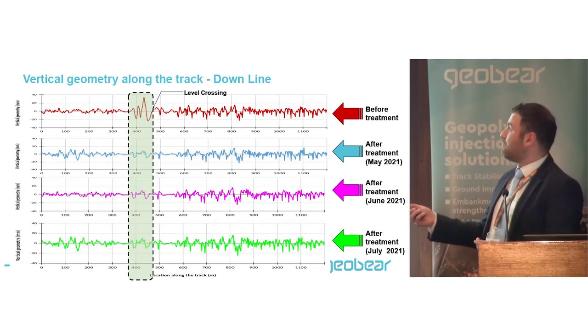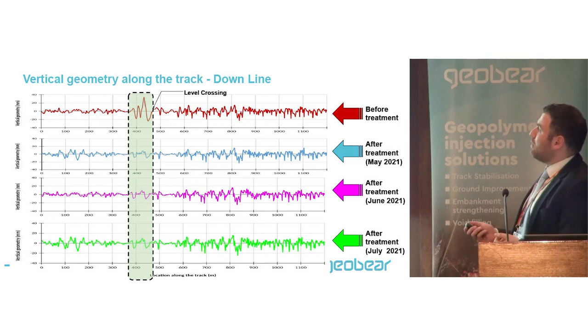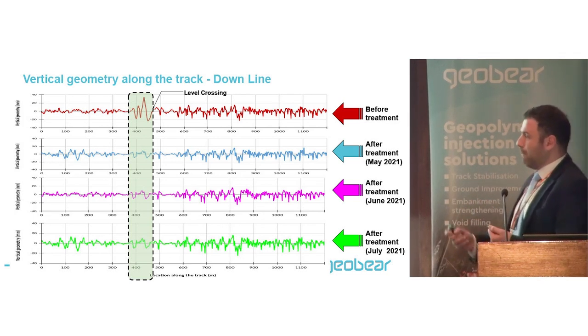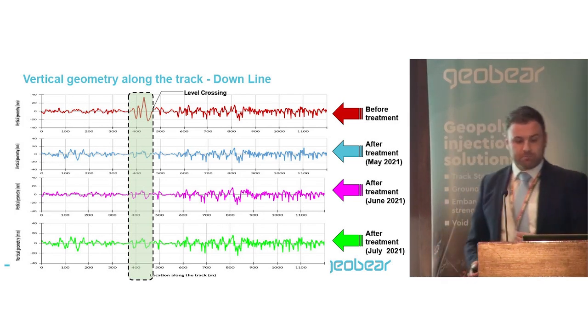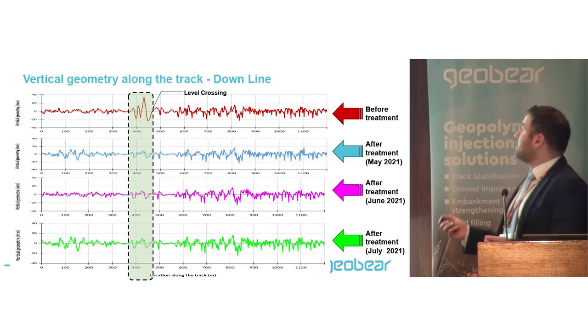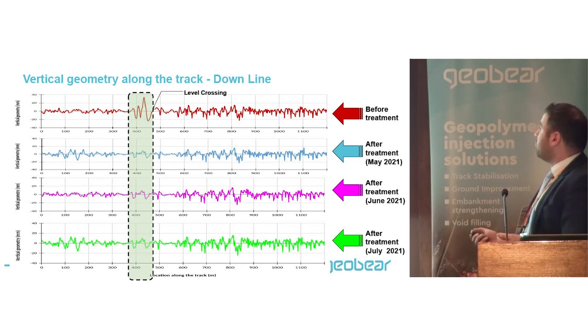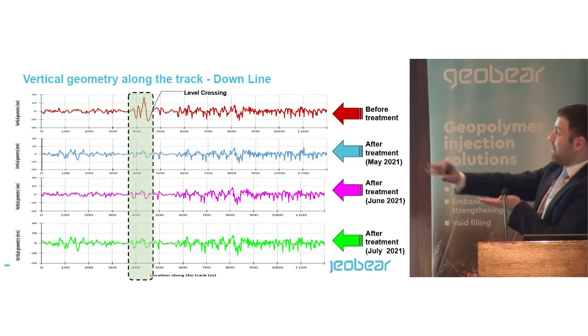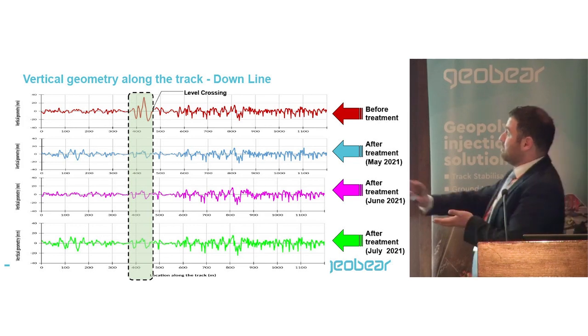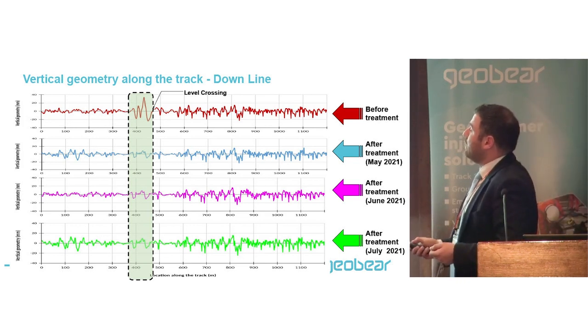So the red curve represents the track geometry response before the treatment, and the green highlighted area is the area of the level crossing. You can see a significant response bump as you go through the level crossing - that's before the treatment. After the treatment, run after run, you can see that right after we finished the treatment, we managed to almost level it back and almost eliminate the harsh track geometry response.